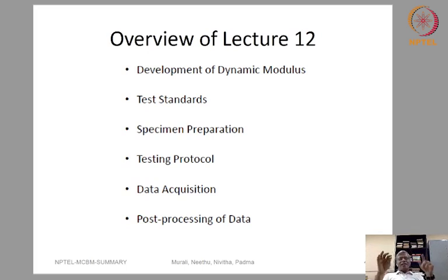One needs to clearly understand that this dynamic modulus test is more or less the de facto standard in North America, and people are now increasingly using it even in Europe. There are advantages of doing this test, because we can go from a low temperature all the way up to 60 degrees centigrade, and for a range of frequencies from 25 hertz to 0.01 hertz. If you recollect the discussion related to master curves given by Dr. Padmarekha, you will understand that you could use this data and fit a master curve. Once you fit a master curve, depending on the location in which you plan to construct your pavement, and the temperature and frequency, you can have the modulus extracted straight away from the master curve.